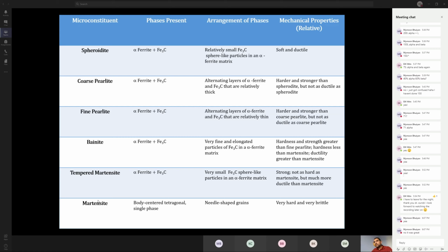If you cool a little bit faster, you get the fine pearlite where the spacing of the lamella in the pearlite is smaller. So this would be stronger than before, but still has good ductility. If you cool even faster, you get something even stronger, the bainite. And if you cool even faster, you get the strongest structure, which is the martensite. But the martensite is also the most brittle structure. So martensite is extremely strong, but it doesn't deform. It snaps, it breaks.